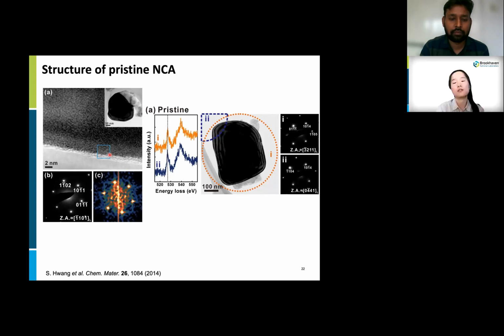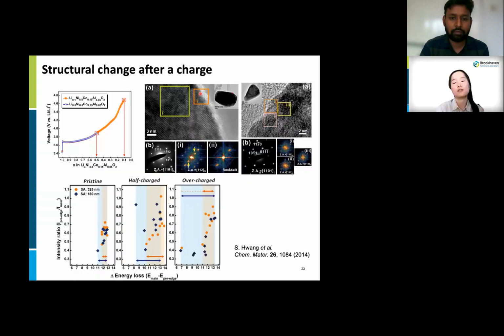And I got oxygen K-edge spectra from multiple particles at each state of charge, and I summarized the data in this plot. And from here, we can see some variations, and these variations become much more severe in the overcharged sample, which means material degradation happened locally and inhomogeneously.